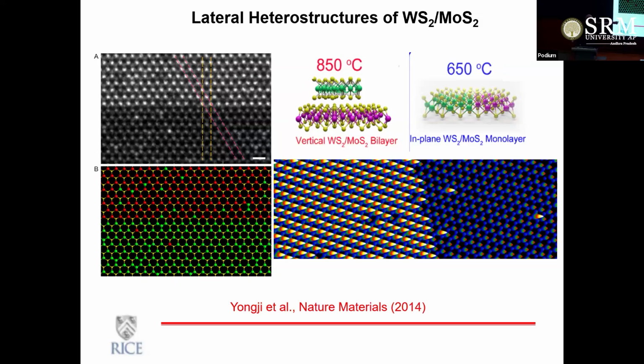So you can see that beautiful atomically sharp interface that is created from combining two different materials, that is tungsten sulfide and molybdenum sulfide, in a single atom thick layer. Now, what is interesting about this is the interface between these two different materials is sometimes not very stable. You can imagine, right? Now you're thinking about materials that are essentially made of surfaces only. So diffusion and other kind of mechanisms can be very prominent here. So you can actually see some of the atoms from this side has ended up in the other side, right? Because the diffusion of atoms can be actually visualized in the TEM.